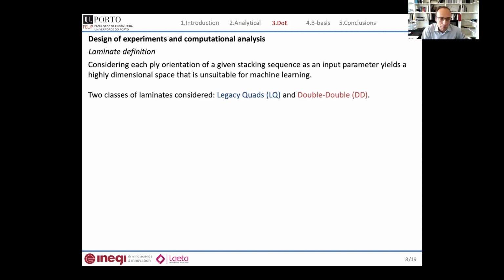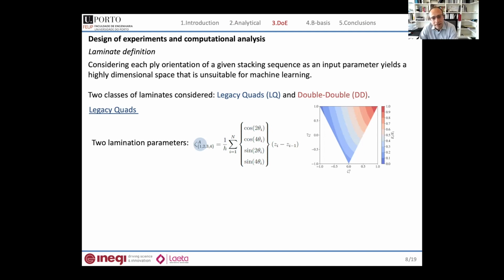So the way that we solve this problem is to consider only two classes of laminates. So the first one is what Steve Tsai named legacy quads. So in the sense that we only use balanced symmetric laminates with only 0, plus or minus 45 and 90-degree fiber orientation angles. And then we use the double-double laminates also proposed by Steve Tsai. So if we do that, we'll see that for the legacy quads, we can use only two lamination parameters, so Xi A1 and 2, to define our laminates, okay?